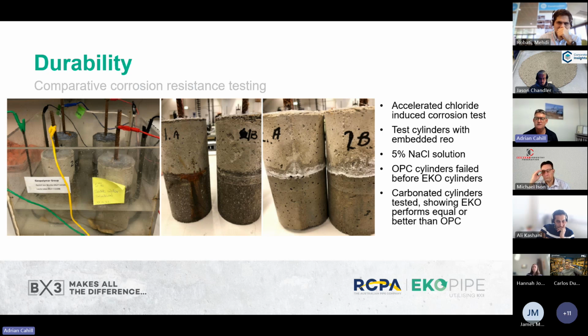The cylinders are then placed in a sodium chloride solution, subject to a current, and basically monitored. They're monitored until they fail. And what we found in the initial testing was that the OPC cylinders were failing consistently before the eco cylinders. We've done a number of these trials so far.